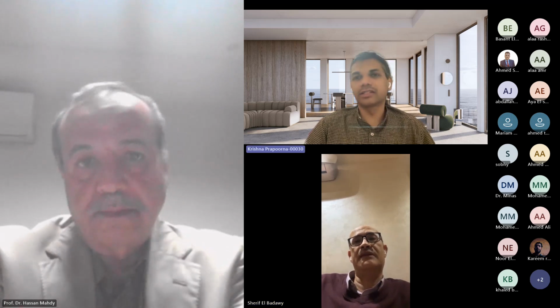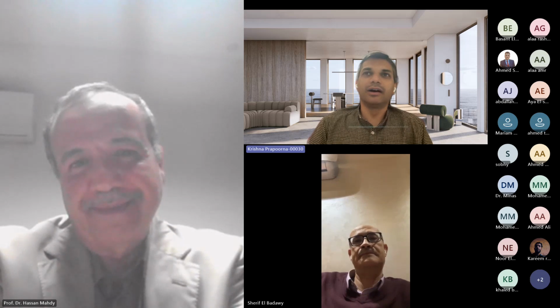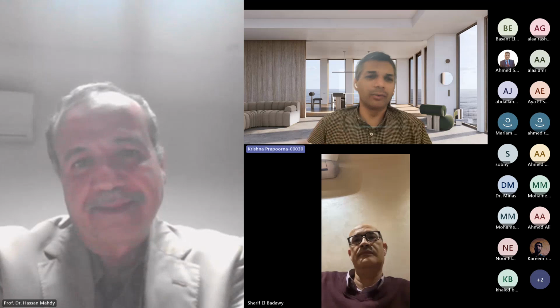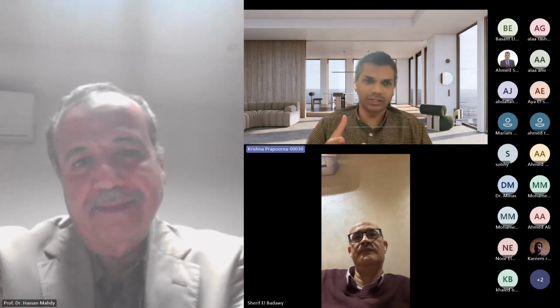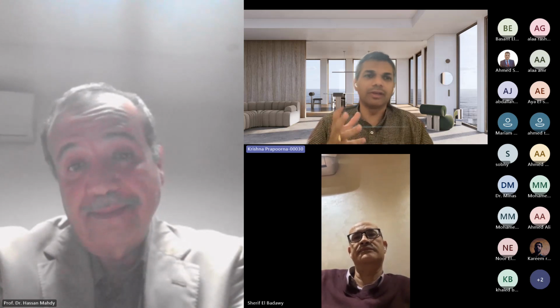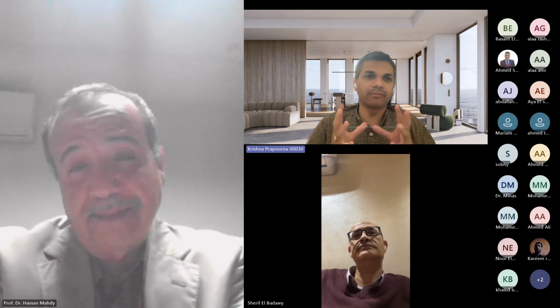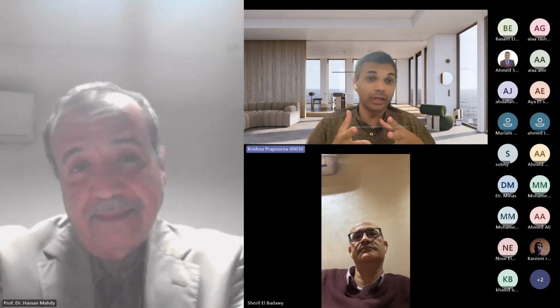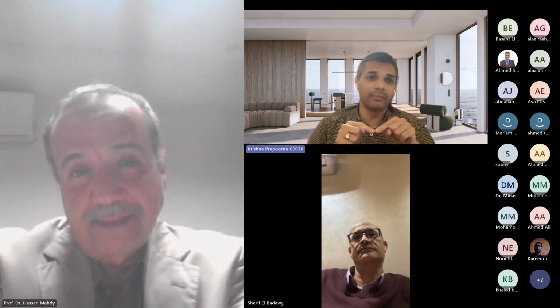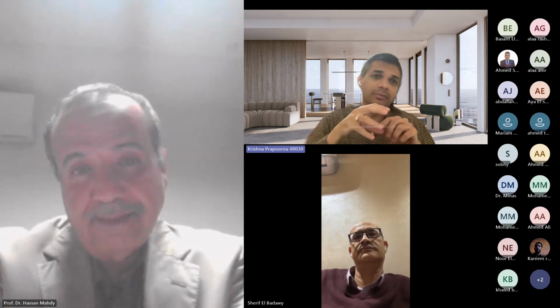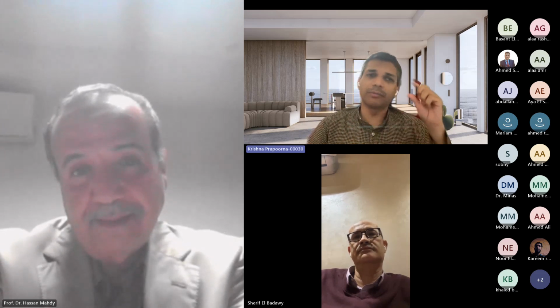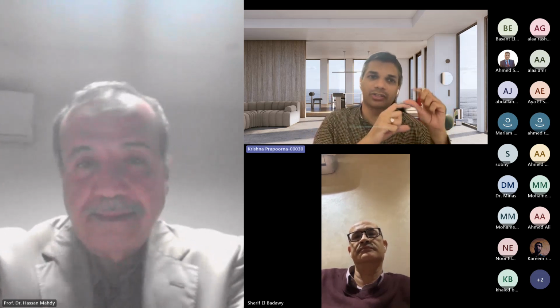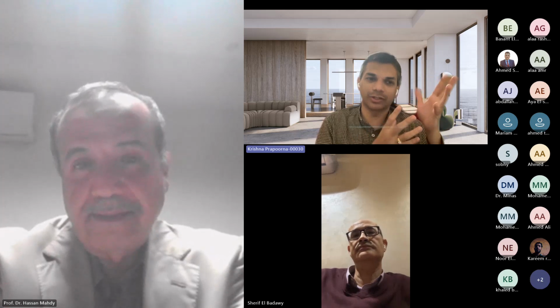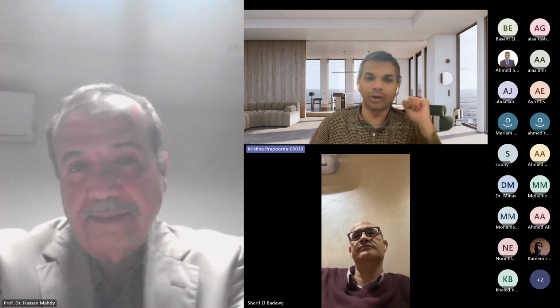Absolutely, that's the intention. In fact, we've had questions in the past when we were developing this pervious concrete. What about high volume roads? Can we come up with a composite structure? So we said we will have a structural base built with M40, M50 concrete. That's what we did. And then we had a groove within them, and then we have now impregnated pervious concrete within them. So it's a functional layer over a structural layer that behaves as a composite structure. So we have now used it in high volume roads.